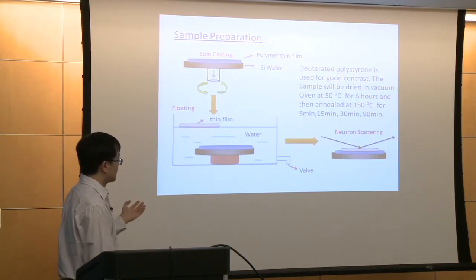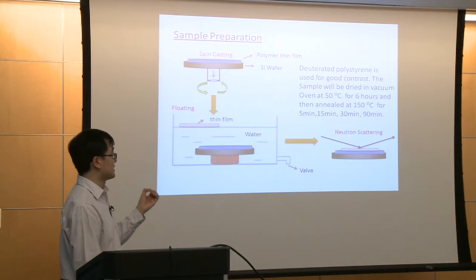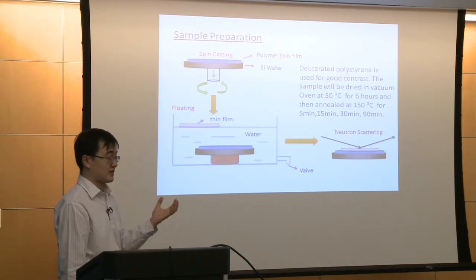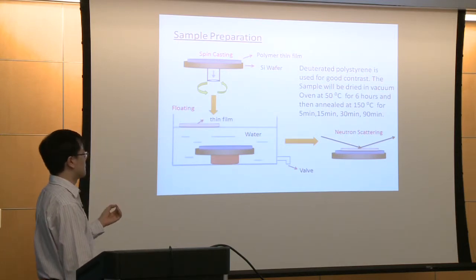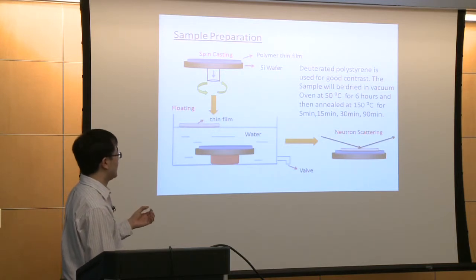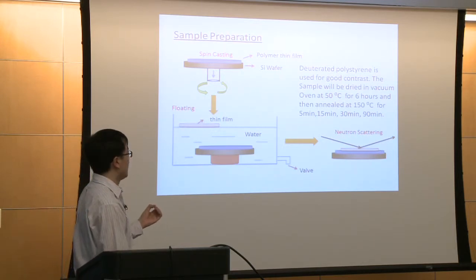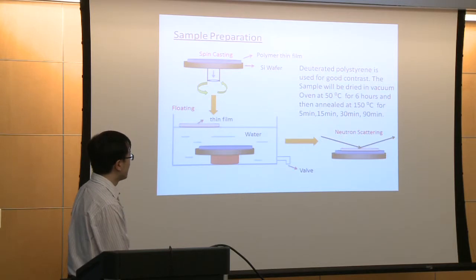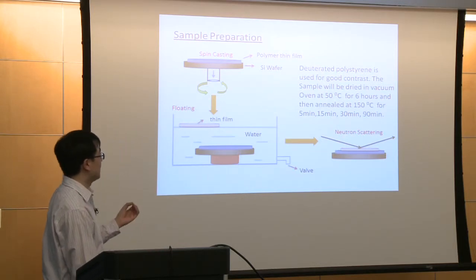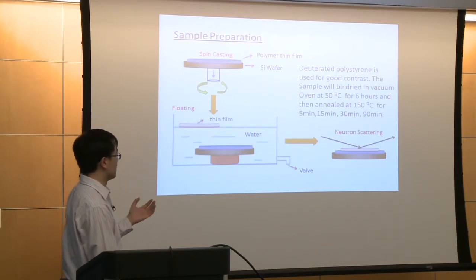And here I need to mention we use deuterated polystyrene instead of the normal polystyrene for the purpose of good contrast. And the sample will be dried in the vacuum oven at 50 degrees C for 6 hours and then annealed at 150 degrees C for different times.